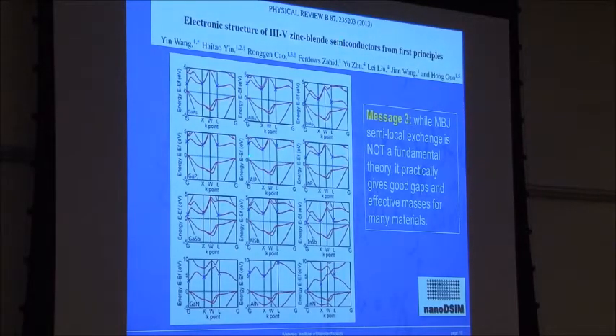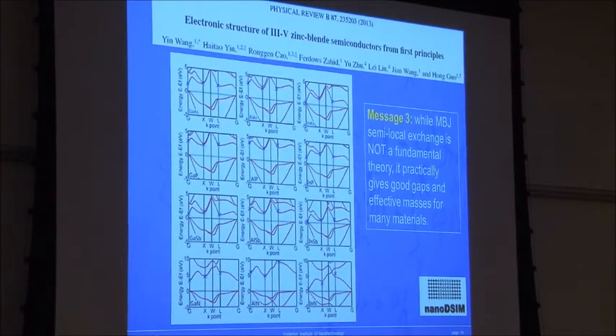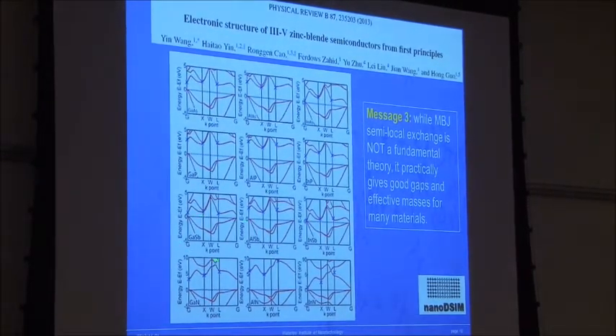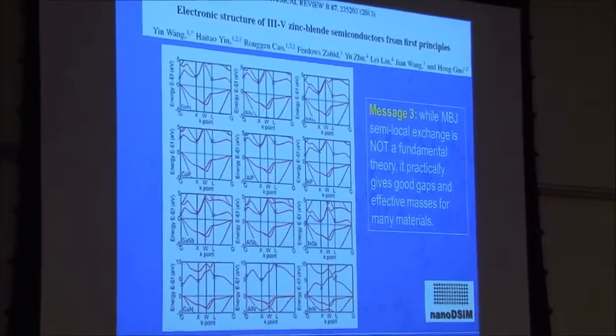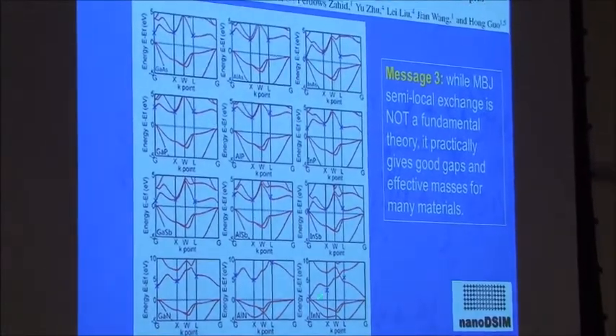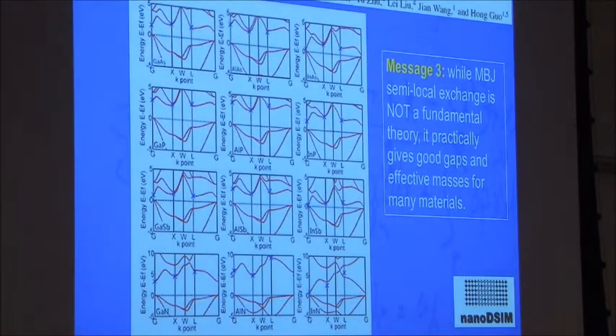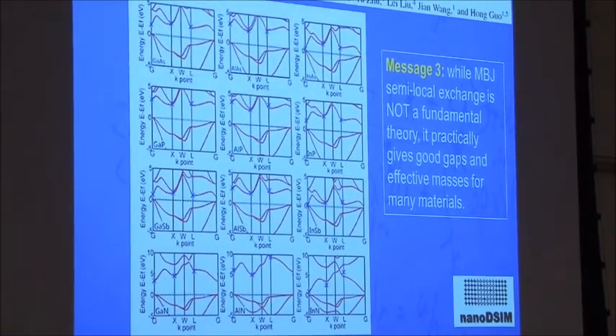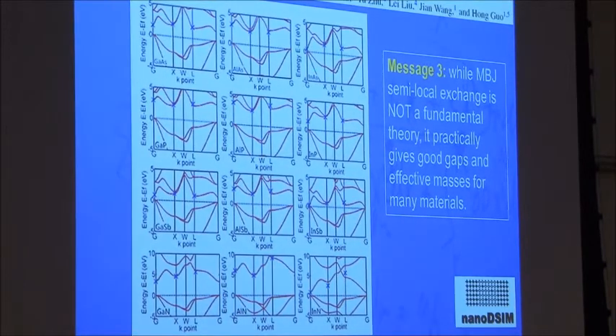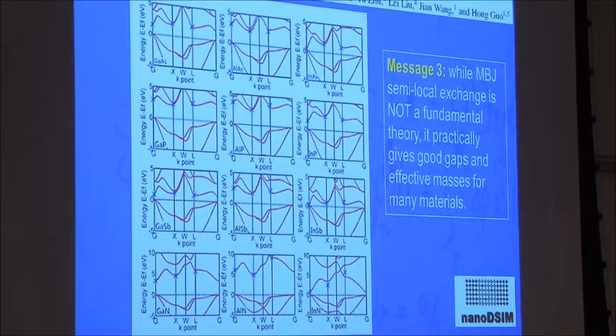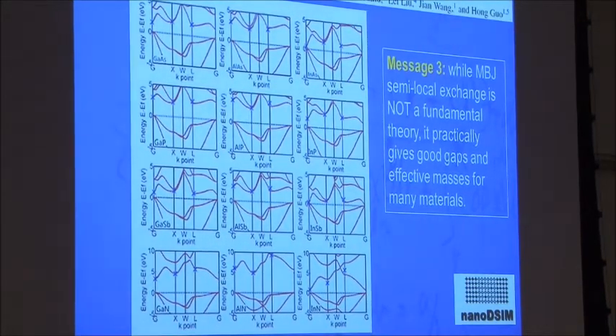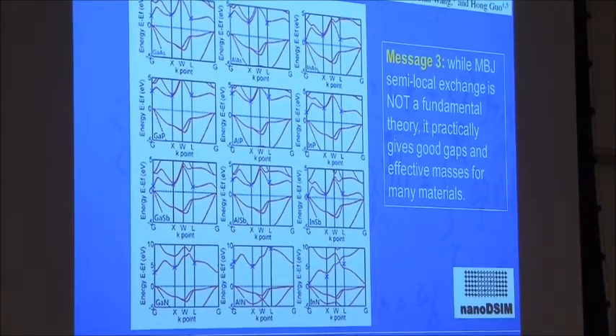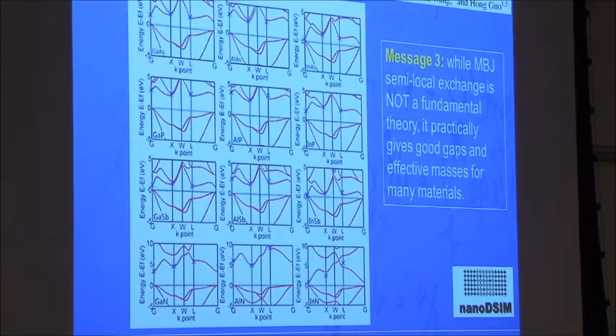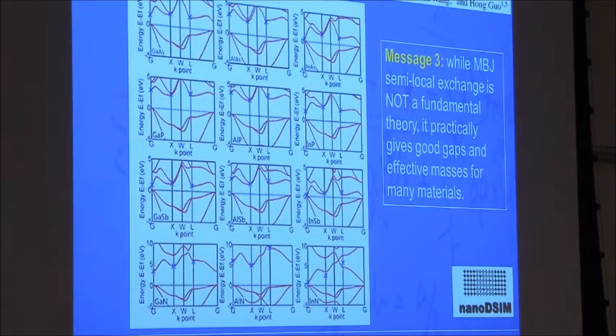So this year we calculated all the zinc blende III-Vs, and you can see that our calculated band gaps, band structure, the red line, compared with the experimental data, are just right on for many compounds. So the message is that this modified Becke-Johnson potential, if you work at it, you can make it work for at least III-Vs. It works for silicon and many other systems. We calculated about 30 compounds, and it works very nicely. It does not always work. If you want to work on copper oxide or something, it will give you something wrong. So this is not a first principles theory, but for semiconductor physics, this works. So we can use it for many device simulations if you know what you're doing.